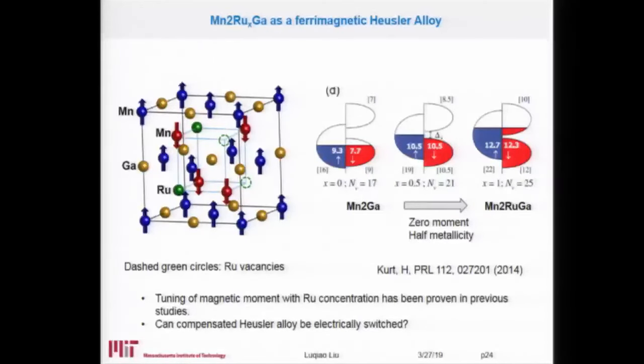What people found is that if you intentionally make some ruthenium vacancies in those materials, you can tune the Fermi level of this system. And if you adjust the ruthenium concentration correctly, you can put the Fermi level in a certain position so that spin up and spin down bands are equally occupied. So in the end, you have zero net magnetic moment. But they also argue that in this specific case, the Fermi level falls into the gap of the minority band. That means you have 100% spin polarization at the Fermi level. So it's a half metal. At the Fermi level, you only see one specific type of spin. This would be ideal because you have two promising properties: one is zero moment, and the other is 100% spin polarization.